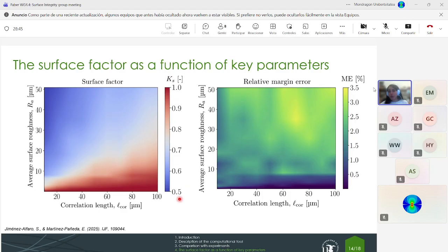And since we are working with a stochastic problem, we also need to analyze the relative margin of error. And this is what we have done here. You can see here the relative margin of error as a function of the average surface roughness and also the correlation length. You can see that in all of this graphic, the value is less than 3.5%. Indeed, this is because we have imposed a condition, I remind you, that this margin of error needs to be less than 5%. So this is why we have this value. And also you can see that this relative margin of error arrives at its biggest value for a big value of the correlation length and also a big value of the average surface roughness.